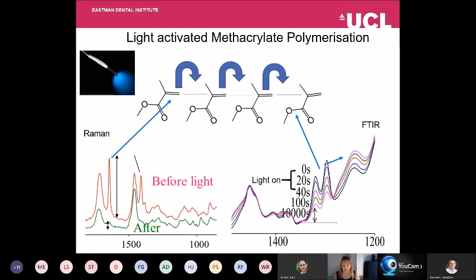What we're also doing is developing an infrared technique that allows us to quantify how fast the process goes. What people often do with infrared is use a peak that's due to the C=C bond in the infrared spectrum, but that's not useful to use if you've got water present because the peaks are overlapping. So what we're using is a different peak that's due to vibration of a carbon-oxygen bond. What happens is when the monomer polymerizes, that peak shifts. And so again, we can use the height of this peak to see how quickly the process is going.